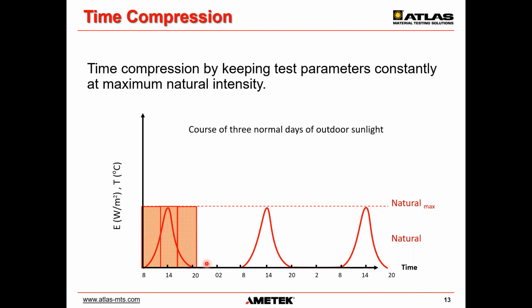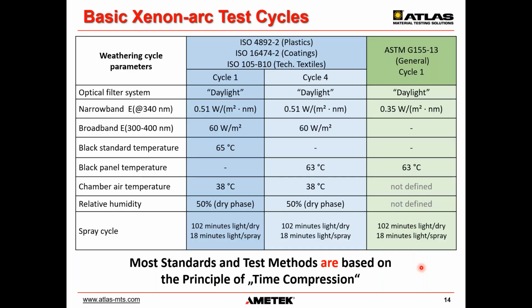And then we have the same integral here, which is the radiant exposure, because this is the irradiance and this is the time. I just told you that irradiance integrated over a time is the radiant exposure. And then we get to this same integral here, but in a shorter time. And this is called time compression. So for the compressed test, the time to reach a specific radiant exposure is much shorter than outdoors. That's the whole trick.